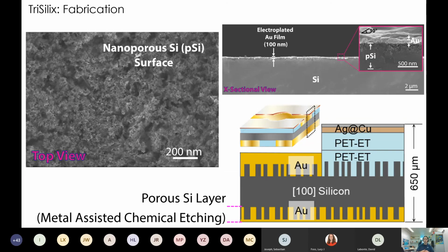And then aside from that, when we do thermal bonding, again, there is structure on the surface that if we take a thermoplastic film, we can just simply heat press it and then create a barrier layer or an insulation or an isolation layer. So we went from all kinds of vacuum-based deposition processes to something as simple as a wet etching process and wet deposition / thermal bonding process. And this is really the backbone of the TriSilix chip.